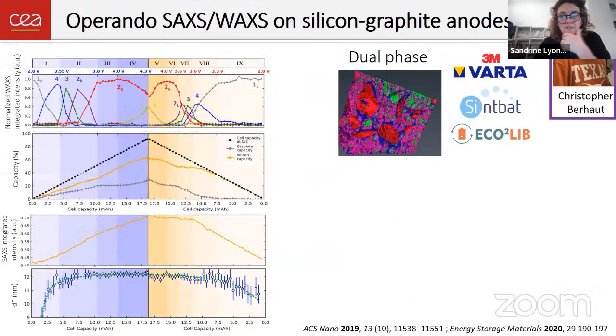If you quantify those data, you get a full understanding of what happens during lithiation, purple data, and delithiation, the orange data. And you get a number of steps that correspond to the formation of different phases in the graphite. This is coming from the WAXS data analysis. And you get also understanding of what happens in the silicon. And in particular, let me just pinpoint here that we are able to measure the swelling that is nonlinear of the silicon phase in the range of 10 nanometers.